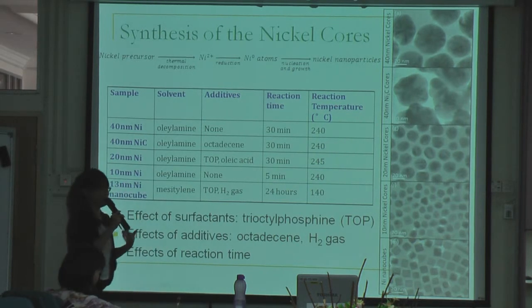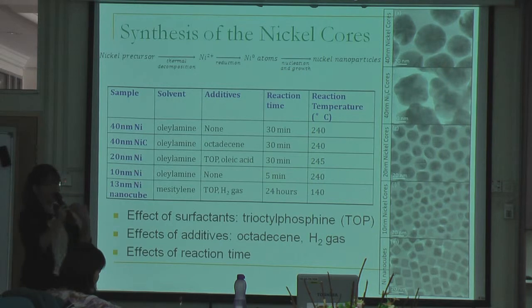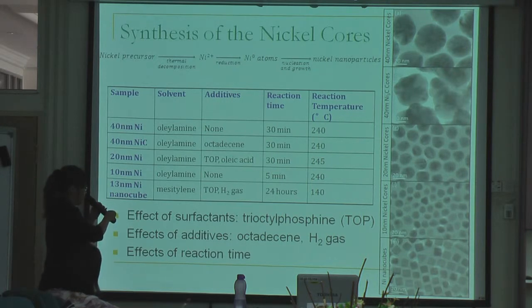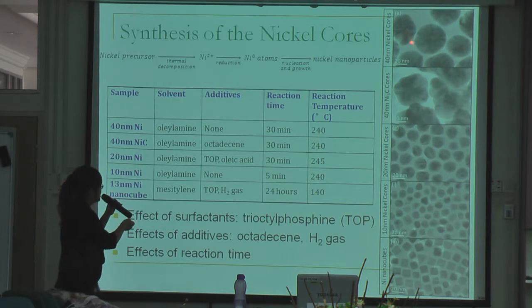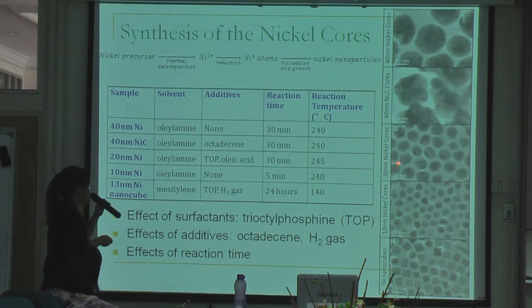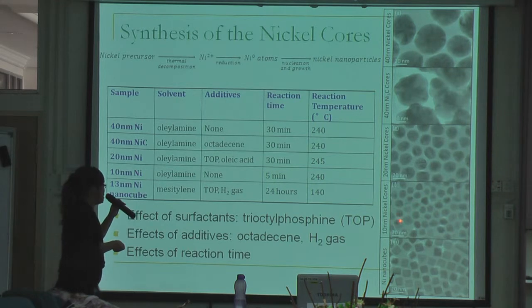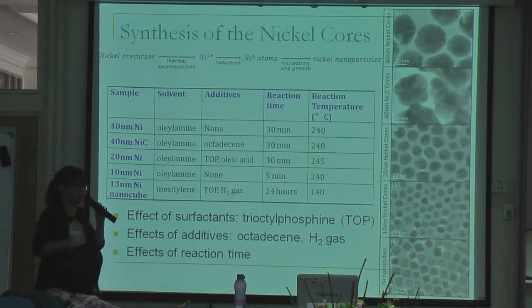The first step of the preparation of the composite is to prepare the nickel nanoparticles. During my research, I was able to prepare 5 types of nickel particles with different size, different composition, and different shape. As you can see from the TEM images on the right hand side, the first one is spherical nickel nanoparticles of about 40 nanometers in size, then nickel carbide about 40 nanometers in size, smaller nickel particles of about 20 nanometers, even smaller at 10 nanometers, and also cube-shaped nickel nanoparticles.